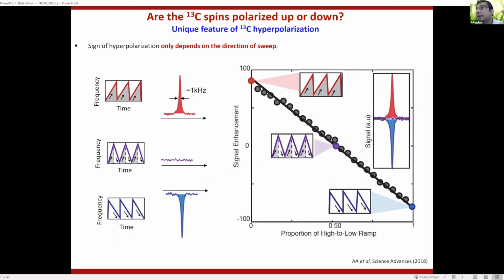We have a weak magnet here. This magnet is a refrigerator magnet, about 10 millitesla or so. But the spins polarize aligned or anti-aligned to this magnet, or anywhere in between, just by the direction of these microwave sweeps that you apply. And these microwave sweeps are very low power, very low frequency. You're almost tickling the spins, but you can make them very highly polarized through them.